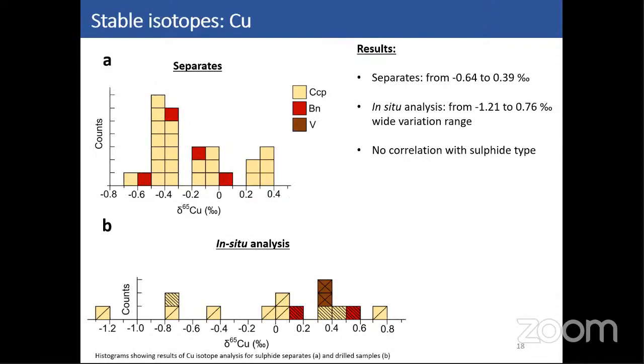Concerning the results of the isotope analysis, first of all for copper, the first thing that we see is that the variation range for in situ samples is much wider than for separates. Separates range only from -0.64 to 0.39, while in situ samples range from -1.21 to 0.76, which is quite big. Moreover, as you can see, there is no correlation between sulfide types and the copper isotopic composition. Here, for instance, in situ samples with a simple bar are magmatic samples, stripes are hydrothermal ones, and crosses are alteration. So as you can see, there is absolutely no pattern.